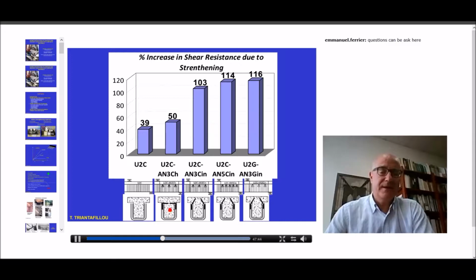So this is better. But it gets much better if anchorage is according to the way that I described before. That is, if we use those spike anchors with half of their length inside the slab, so that stresses are directly transferred from the jacket to the concrete. Of course, if we decrease the spacing of the anchors, that would be even better. But the main concept is that we need to combine those U-shaped jackets with spike anchors at a reasonable spacing. This is much more effective in comparison with the 3-sided jacket without the anchorage.